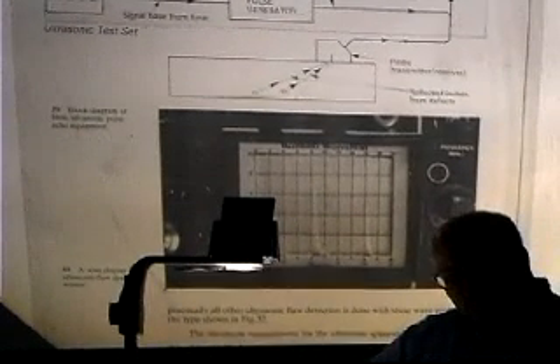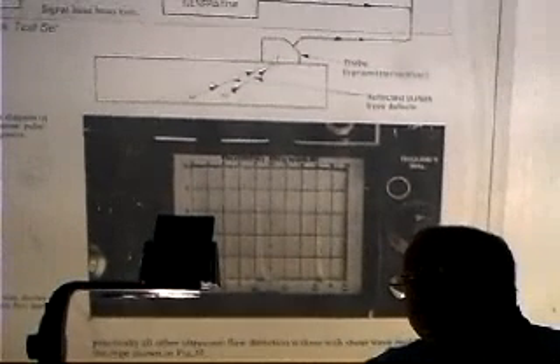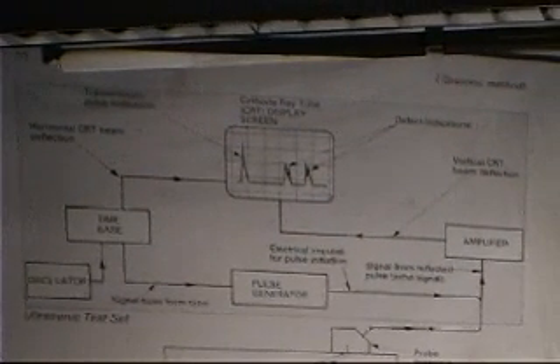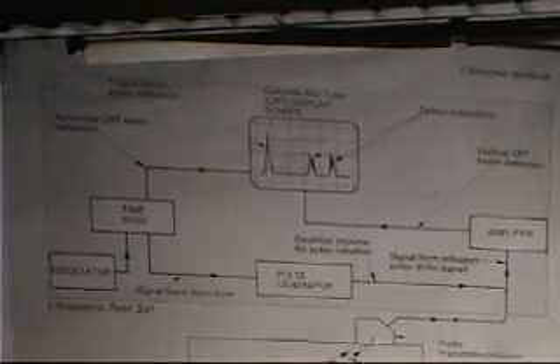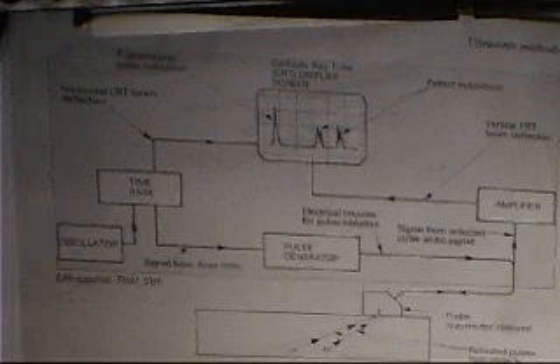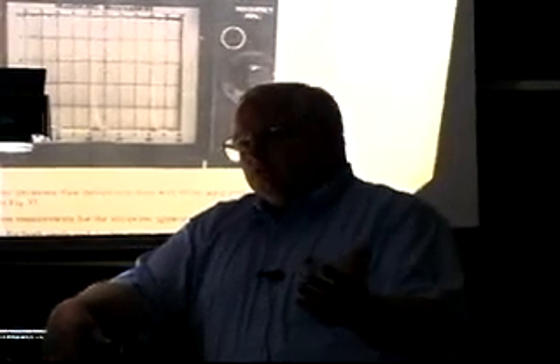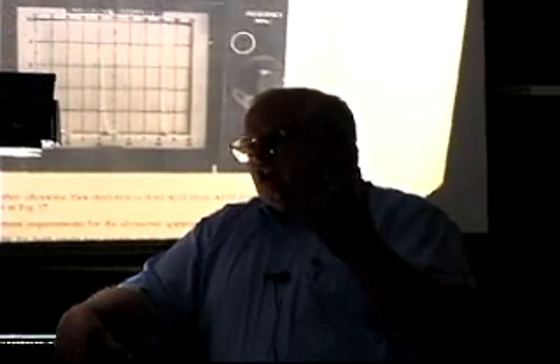Well, the problem was, there actually is a sheet at the steel plant in their records that showed that the ultrasonic technician found this football-shaped defect. In fact, he's got a little drawing of it on the sheet. It shows this kind of 12-inch by 8-inch thing. He sized it with his ultrasonics. And he went in to tell his boss that he had found a flaw. But they had already scrapped 2 of these shafts, and they were only making 8. They were making 6 for the ships and 2 spares for the fleet. And they had already scrapped 2 of them.